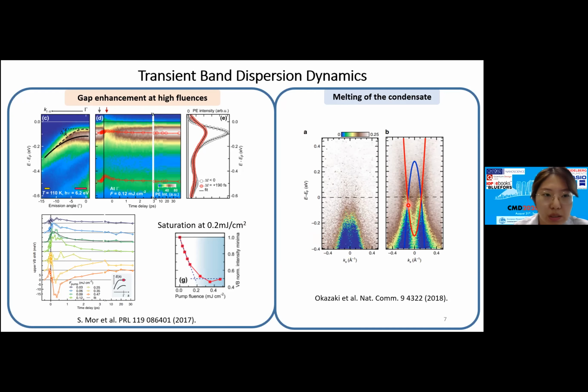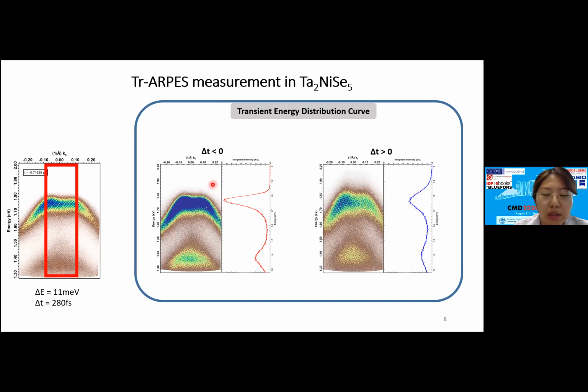To verify this, we want to see the gap dynamics in our measurement. So we reproduced this measurement. This is our result. You can see this video after the pump. You can see the spectral weight changes. Following the previous papers' procedure, we integrated at the center of the band, and we got this energy distribution curve, and you can see the clear different line shape before the pump and after the pump. So firstly, we want to verify the gap enhancement.